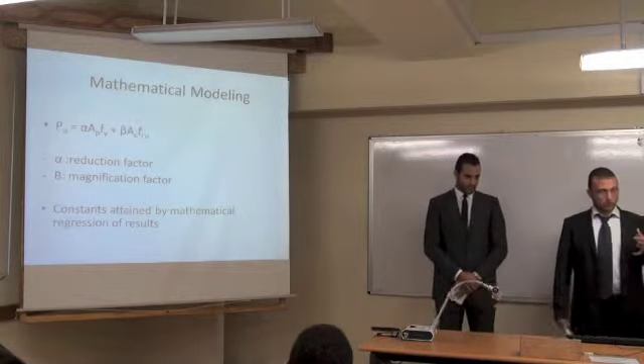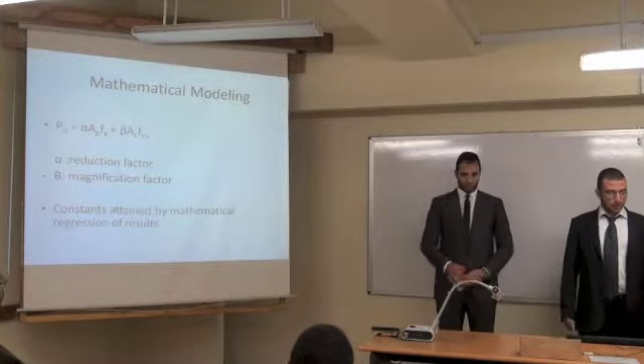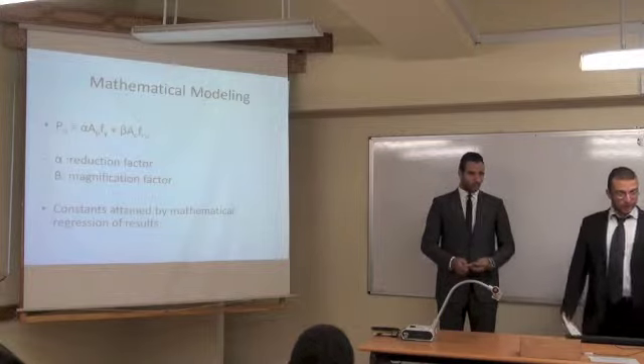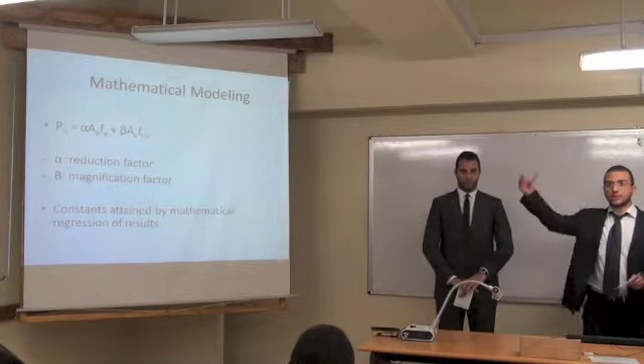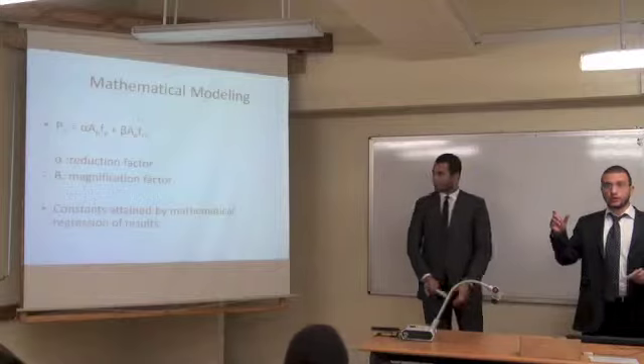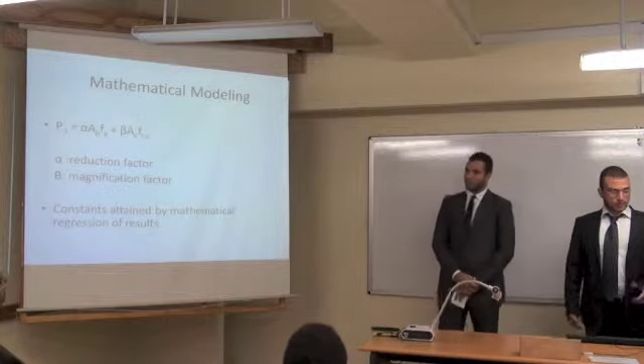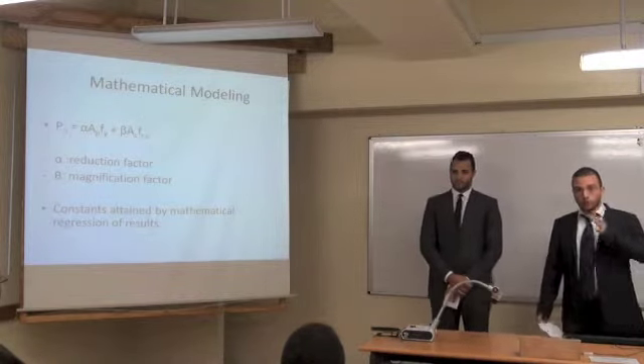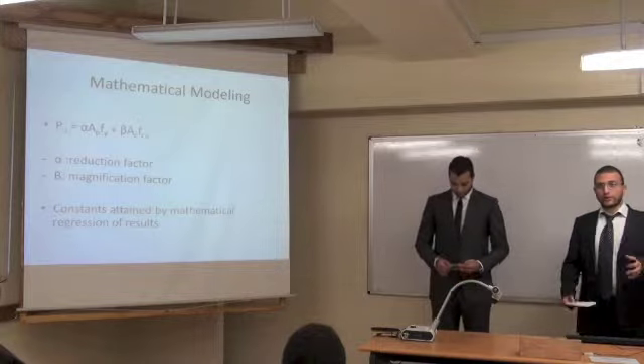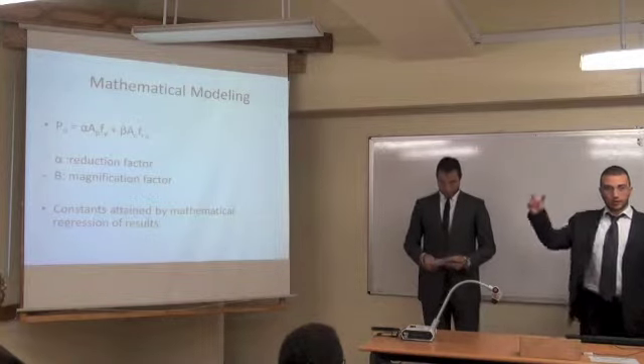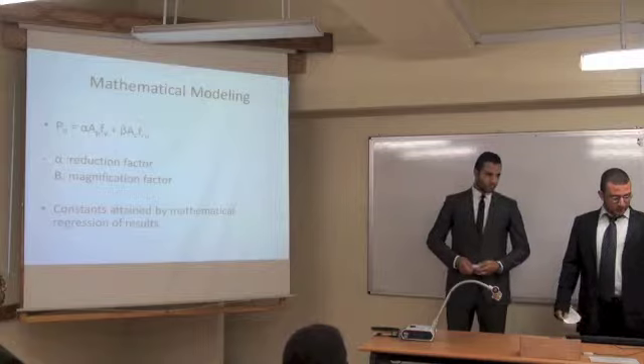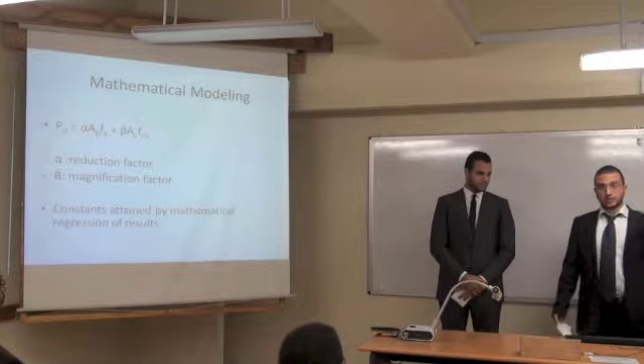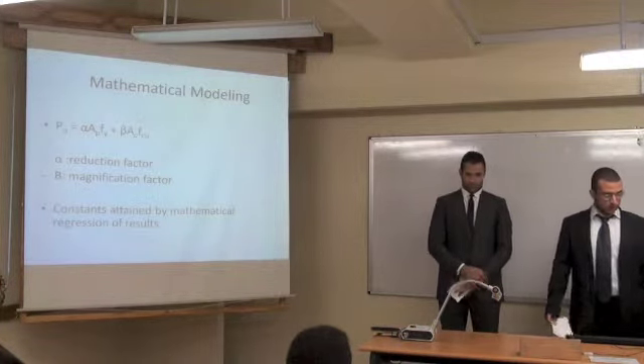After, when we come up with the results, this is the equation we expect to express the strength of the confined concrete tubes. And this experiment was conducted before, or at least from what we found in the literature, on steel tubes. Okay? And based on the theory that was explained at the beginning, this formula was devised.